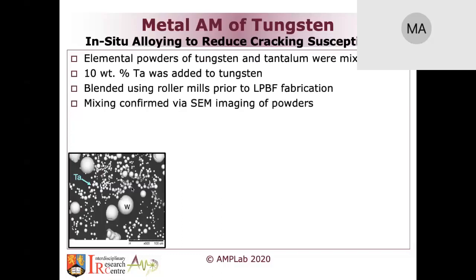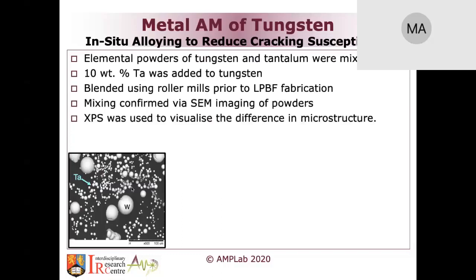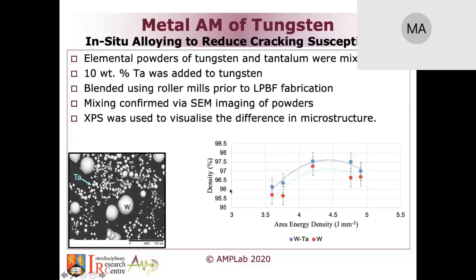And we looked into the density difference. As you can see, with the tungsten on its own, the maximum you can get is over there. Whereas when you add more tantalum, you start to densify a little bit more. You gain an extra maybe 0.5% or so by adding a little bit of tantalum into the material.